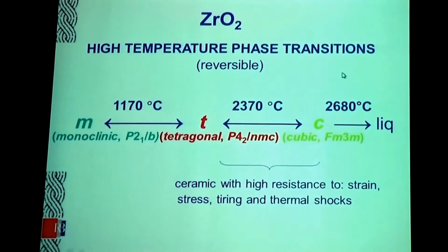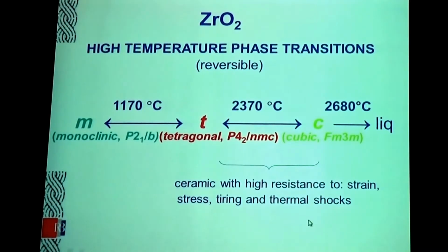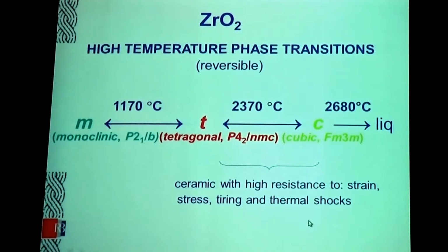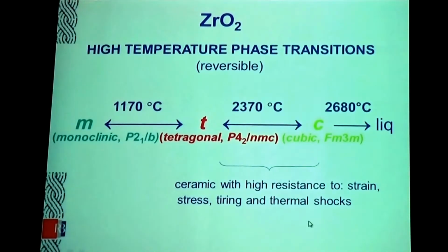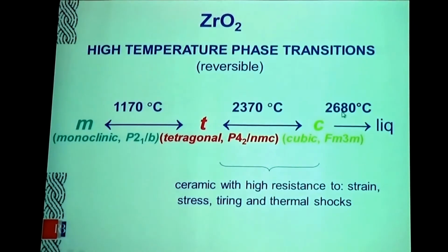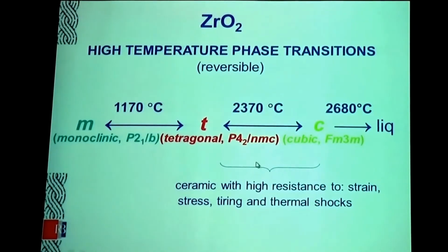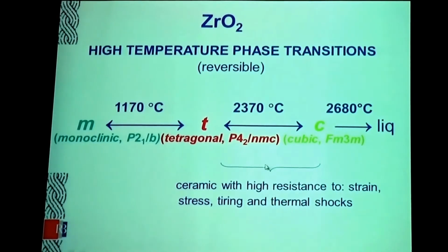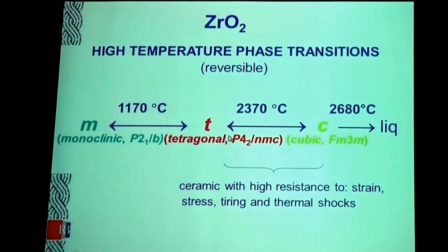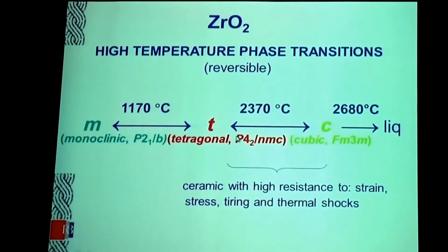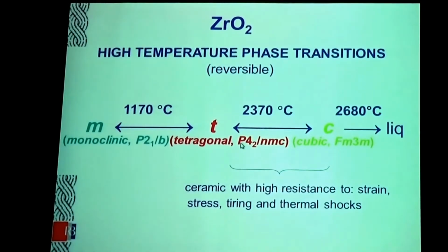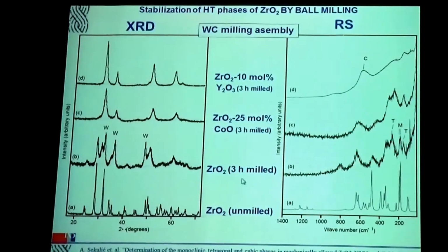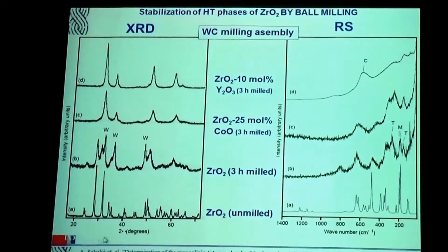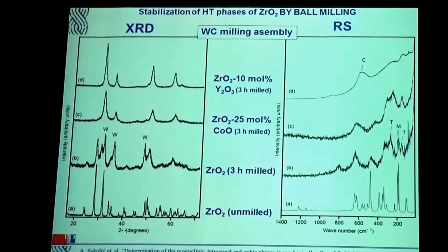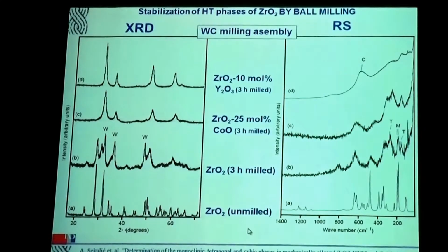So I studied the phase transition in zirconium oxide. I studied also high temperature phase transition, but this was phase transition induced by stabilization of tetragonal and cubic phase. As you know, these phases have much higher resistance, especially tetragonal phase, which is the best for hard ceramics and bone implants. This was still under my maiden name, so this was very far ago.